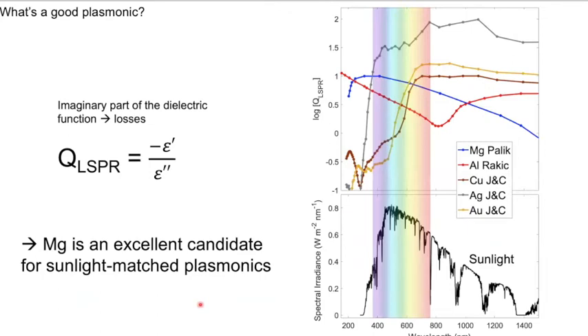A lot of people are trying to find ways to quantify the goodness of a plasmonic. And one of the parameters that I like is this quality factor. And the quality factor is just basically the ratio of the real to imaginary part. So it tells you, again, you want a small imaginary part. And I've plotted this here as a log of that quality factor. And what I've done here is that I'm showing you where the visible range is and where the sunlight shines. If we want to do anything with energy, we're going to want to have it matched with sunlight. And well, you can see that silver is really good.